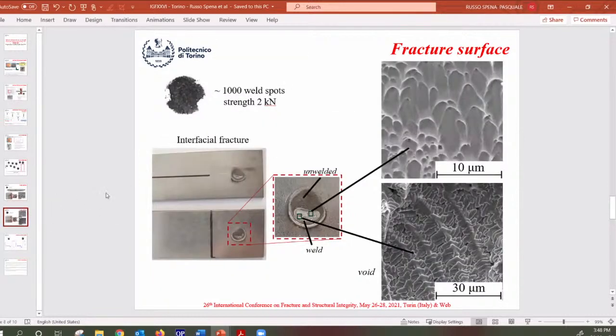Instead, here you can see which was the problem related to the electrode wear, and particularly related to the fact that an electrode with this level of wear was responsible for incomplete welded joints with a cross section that was represented by an unwelded area and a welded area with some defects. For instance, you can see that even if the fracture was ductile in this region of the spots, in other regions there were many voids characterized by this typical surface appearance due to the final solidification in these voids.